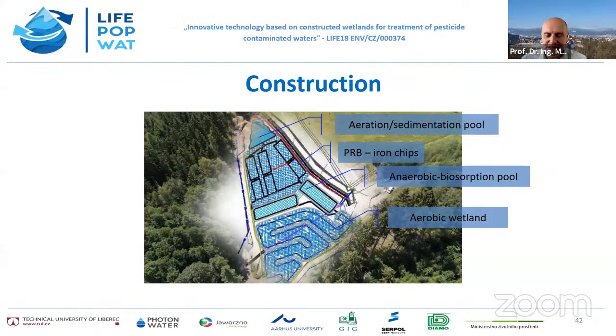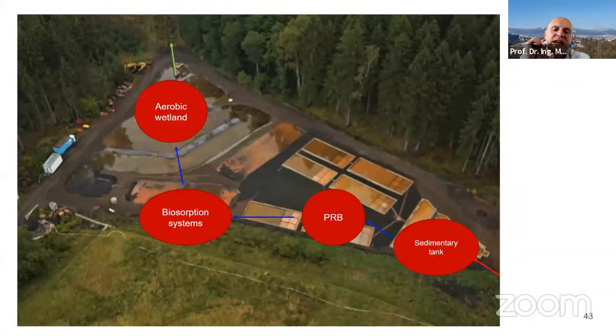So our idea is, at the bottom of this pile, to make a system which is based on a few steps. The first is aeration and sedimentation pool. Then we have the reactive barrier with iron chips. Then we have an anaerobic biosorption unit, and the last step is the aerobic wetland for final treatment of water. And this is how the site looks in full size here, where we have the injection of water from the right side through the sedimentation tanks, the reactive barrier pools, then the biosorption system, and the final aerobic wetland.